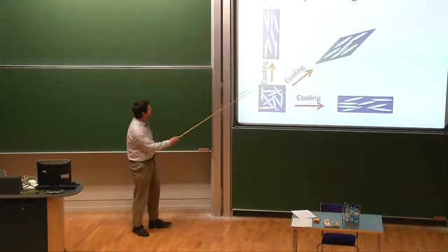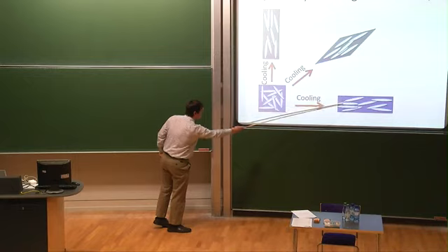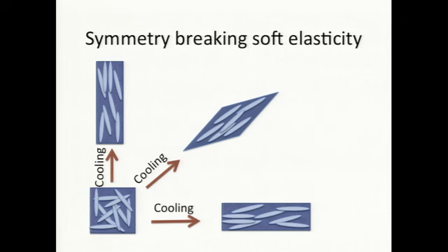Consequently, if you take this state, you can deform it around this ring into this state. It's important to realize that these two are not related by rotation; they really are related by a mechanical stretch, a real shape change. That's a bit more obvious if you imagine the intermediate state. But nonetheless, the rods can rotate, and this change in shape can be accommodated without any additional energy being paid.